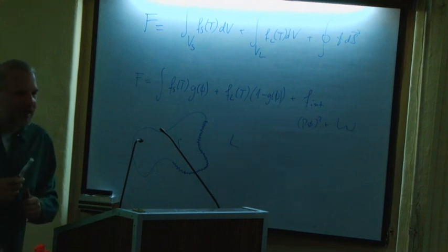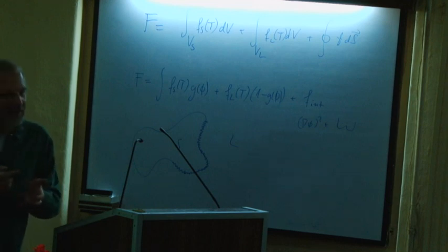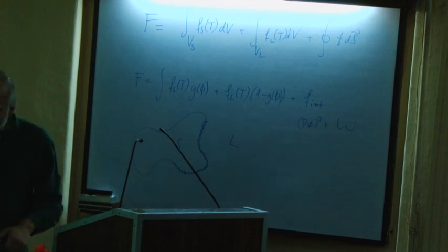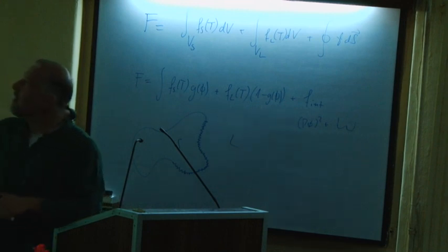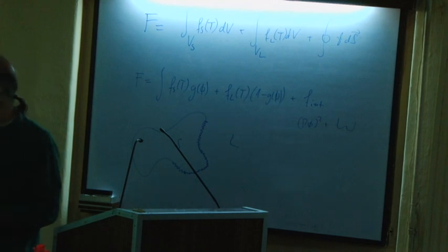But there is one thing that is conserved because, well, if you change the crystal structure, you change the entropy. So this is linked to a change in energy. So we have to take into account energy conservation. Okay? So the phase field part is easy. It's a non-conserved order parameter. So we write down our favorite Allen-Cahn equation that we have seen many times. Now the equation for the energy is a little bit more complicated.